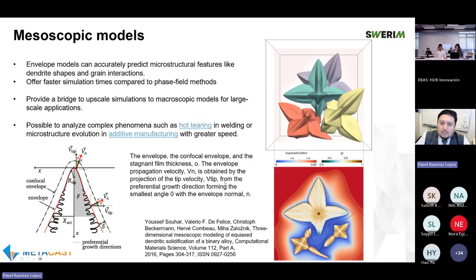Here I mentioned a bit about the approach. You can see why they are faster: instead of resolving all this complexity of the dendrite as we progress with the growth, we are representing this as an envelope over this, shall we say, area. And this allows us to be faster because we are just calculating the velocity of the tip or the solidification front for a more generalized area. And therefore, you get this kind of profiles for the grains, even if you don't resolve exactly the secondary arms.